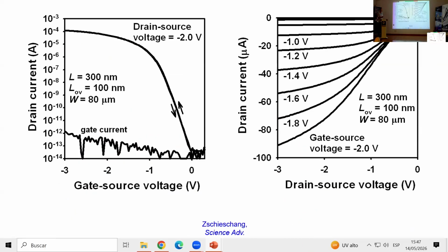Yeah, and then those are the measured current voltage characteristics of such a transistor, having a channel length of 300 nanometers, gate to source and gate to drain overlaps of 100 nanometers, and a channel width of 80 microns. So the first thing we see is that the gate current is in fact very small. Okay, so it's about a picoamp here. So that is a manifestation of the high quality of the gate dielectric, despite the fact that it's only 8 nanometers thick. The second thing we see is that the off-state drain current is in fact at the noise limit of 10 femtoamps. So that's good.